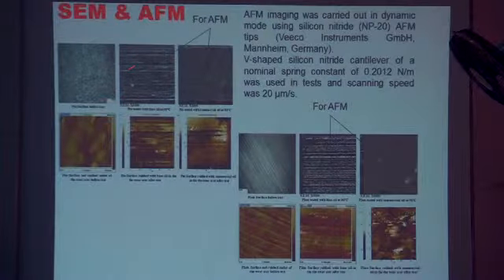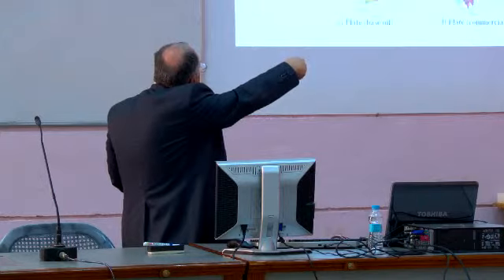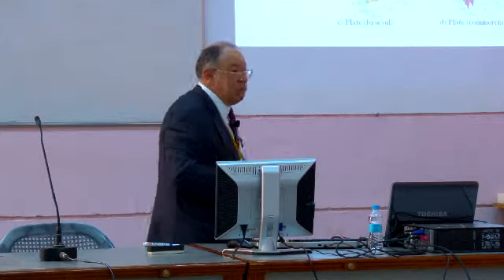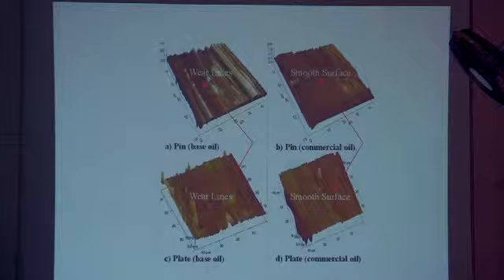This is the optical and SEM microscopy, non-used and used, and we also did AFM. Shortly I will show you better AFM in 3D. What we found is that for the test carried out with base oil, the surface is much more rough. But there is a smooth surface for the test carried out for pin and plate. That's very interesting.